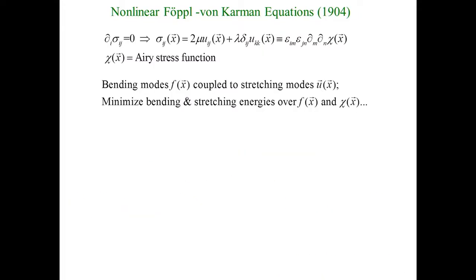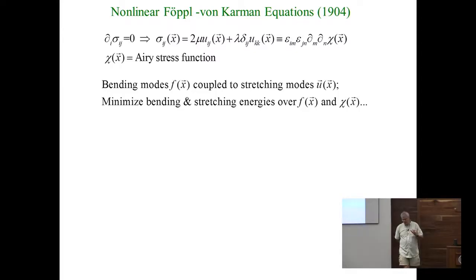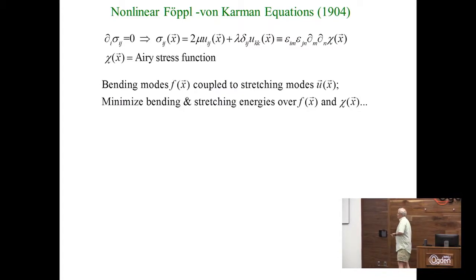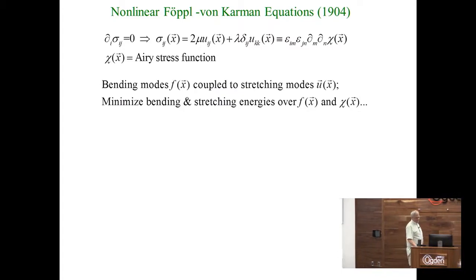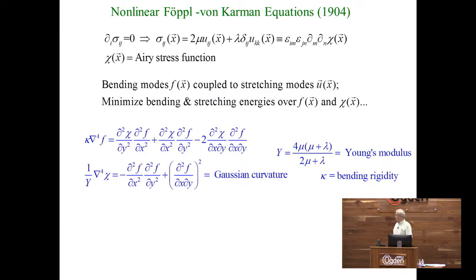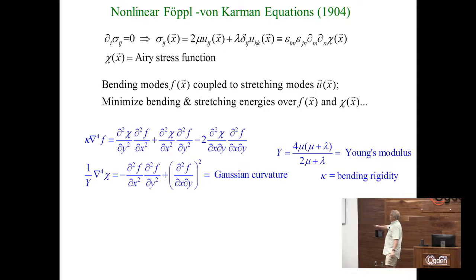So these nonlinear Föppl-von Kármán equations go back to 1904, and if you associate with that stress tensor, that strain tensor rather, Uij, the nonlinear thing here, a stress, the force balance at every little place in the distorted elastic surface is given by this equation, and it's convenient to solve this equation by just setting sigma ij equal to the symmetrized derivative of an Airy stress function. And then we have the bending modes as well. And if you just minimize that energy over F and over the Airy stress function, just do some functional derivatives with Euler-Lagrange equations, you get these things here.